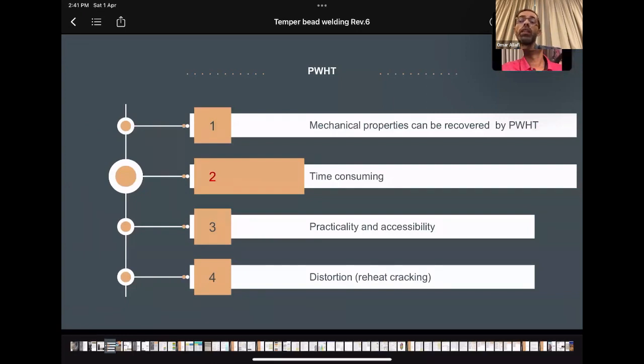So the most critical factor that governs the repair methodology is time. And we know that PWHT is time consuming. In addition to this, it is not always practical, and can itself result in distortion or reheat cracking. So if there is a way to adjust the mechanical properties of the base metal and heat affected zone without the need for PWHT, that would be great. And as we'll see in the upcoming slides, temper bead can do this.